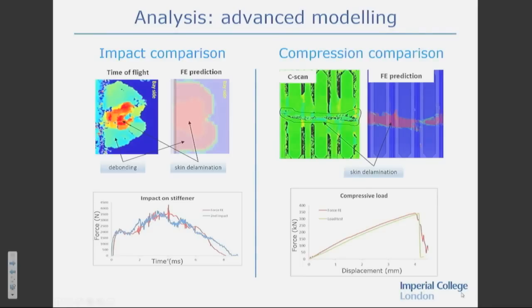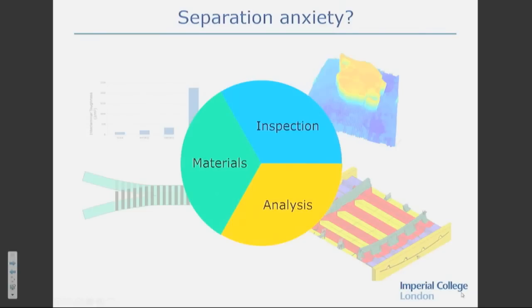More importantly, the behavior in compression: the damage from another ultrasound technique is shown here, and this is from the finite element prediction, running away from where the impacts were. And here is the force displacement, and the green one is the numerical prediction. So extremely good agreement between these. So, for all these reasons, the availability of stronger materials or ways to reinforce the through-thickness direction, the inspection techniques and the range of analysis tools for accurately predicting the behavior, I hope you no longer have separation anxiety.